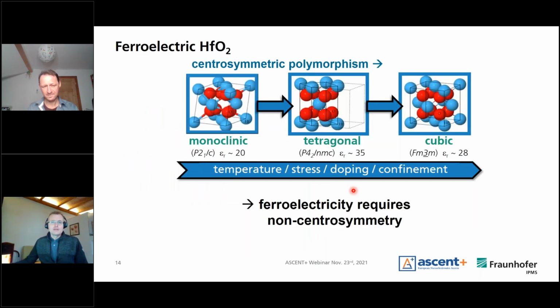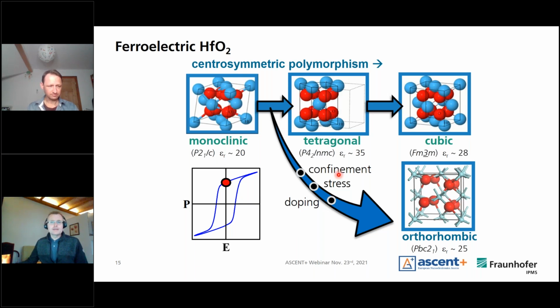And that means hafnium oxide is not from a basic state, also not in a standard crystal lattice. It is not ferroelectric. But if you do specific treatments like doping or stress, and also special temperature treatments, you get it ferroelectric. And this is the orthorhombic crystal phase, which is having the ferroelectric capabilities. All the others, tetragonal and cubic, are non-ferroelectric and show perfect dielectric behavior. Yeah, and if you achieve that, you can exactly do this kind of state switching just by bending internal the crystal, the internal ion, and then you can switch it and achieve the dipoles inside the materials, which also can be read out in other memory concepts.